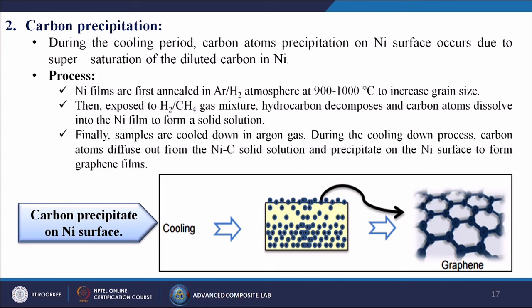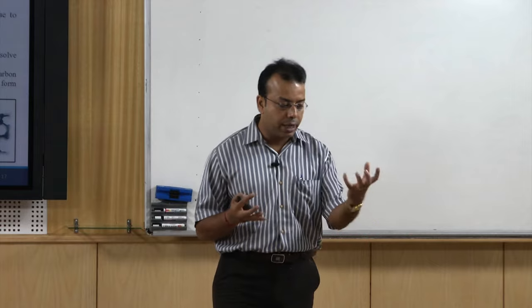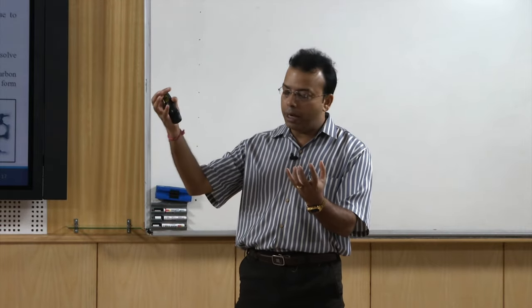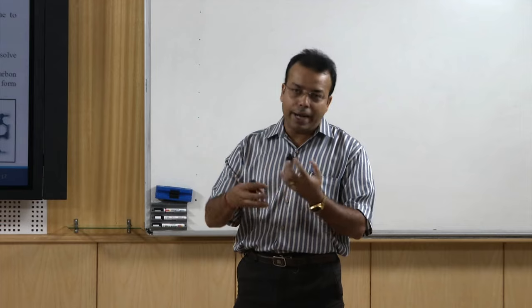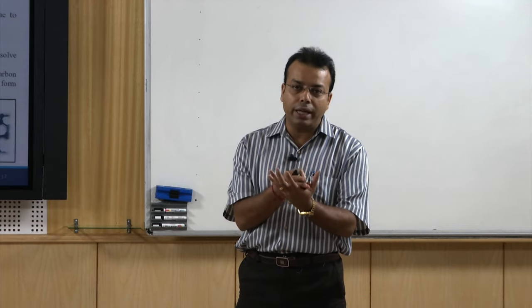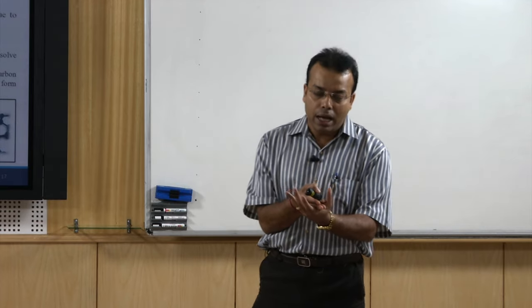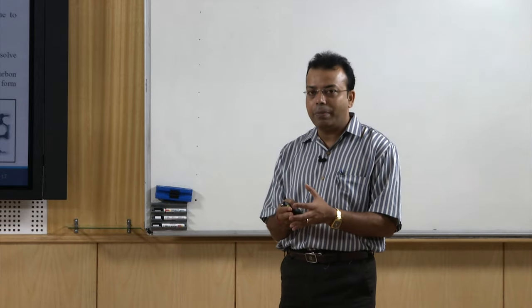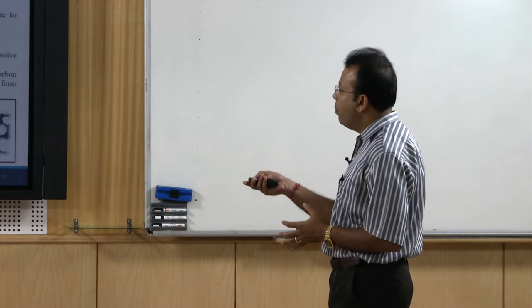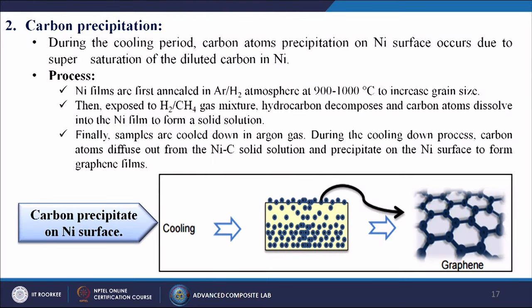Finally, samples are cooled down in argon gas. During the cooling down process, carbon atoms diffuse out from the nickel carbon solid solution and precipitate on the nickel surface to form the graphene films. So, actually, first we take the nickel substrate, then we purge the methane gas, then carbon atoms form and go inside the nickel material. Then when we cool that material, the carbon comes out and the graphene is deposited onto the nickel surface itself.